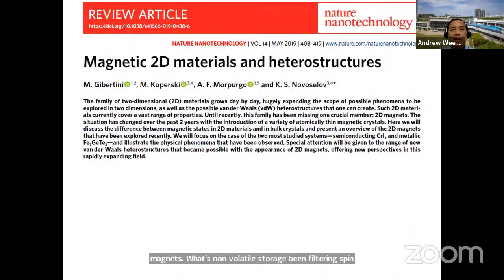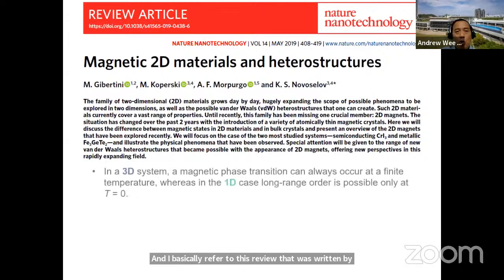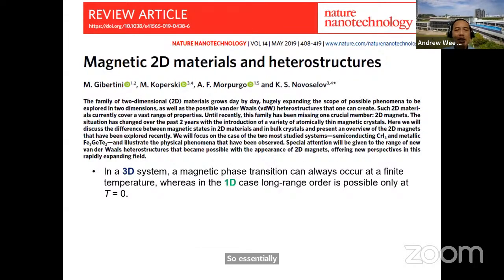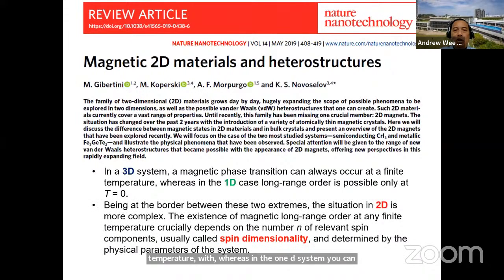Okay, let me say more about 2D magnetic materials. And I basically refer to this review that was written by Novoselov and his group. So essentially, physics tells us that in a 3D system, we always get a magnetic phase transition at a finite temperature. Whereas in a 1D system, you can only get long-range order at T equals zero. And in the 2D system, which is at the border between the 3D and 1D, the existence of magnetic long-range order at any finite temperature depends crucially on a parameter known as spin dimensionality N. So in 2D materials, things are less straightforward.